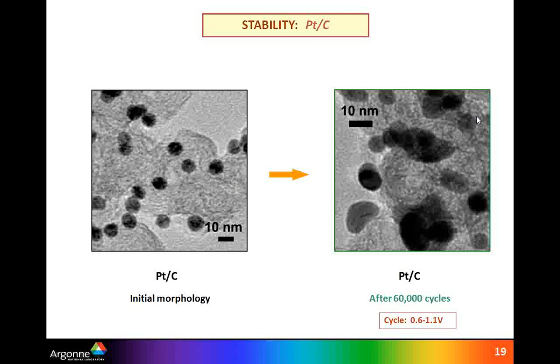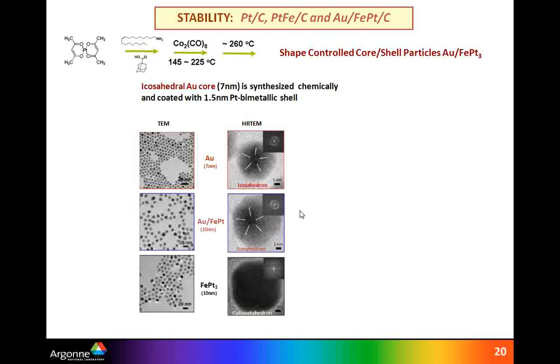And here is a typical example of how pure platinum catalyst looks like before and after 60,000 cycles. So morphology is substantially changed. And for that reason, we introduced concept of multimetallic particles, and our goal was to see whether additional elements such as gold can change how the mechanism of improvement is going to work and is going to affect catalytic and durability properties. So in this particular case, we used gold seeds, and then we covered gold seeds with bimetallic shell, in this particular case platinum iron.